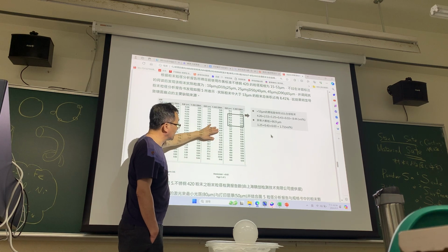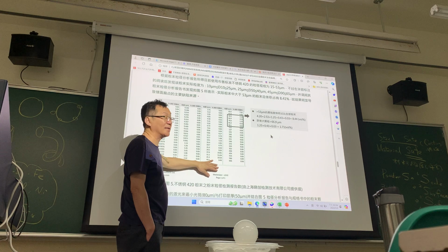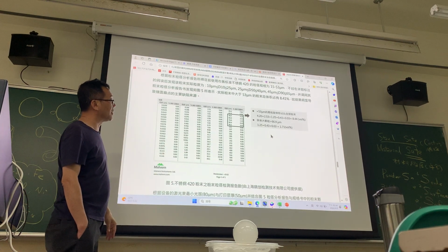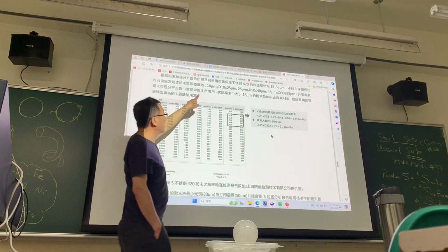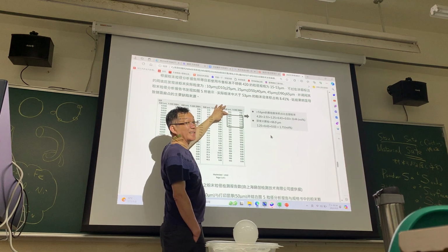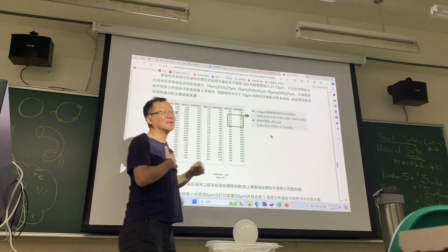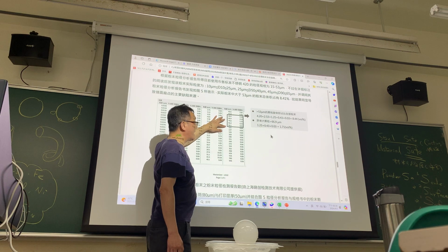So this one, maybe 50%, is what we call D50. Okay. Then you just check. Most people talking about big size say it is smaller. We just found the problem is over this one, the D90. Everybody just says, oh, the D90 is not so big. But they forget about from D90 to D99.